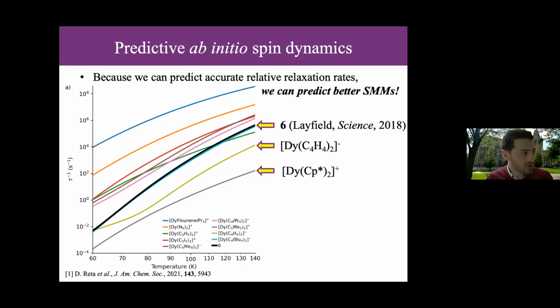So, Kévin mentioned SMMs in MOFs. Here's a challenge to you all: try and get this in a MOF. That might be a nice way of protecting it from coordinating small molecules. Who knows? So there are some nice synthetic challenges here. But of course, cyclobutadienyl is an obvious target because you now have a C4 ring, which is a 2- dianion as an aromatic anion. And so you have a much higher charge that you're putting close to your dysprosium, so the crystal field should be much bigger.